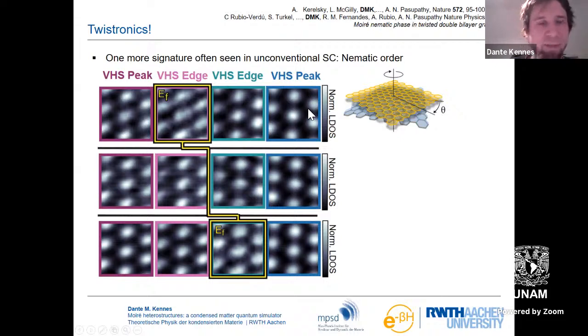So these are STM measurements. You can think of this as probing the local density of states. And let's first look at this far right panel here. This is at a filling where you are far away from this insulating state. And what you see is a nice C3 symmetric pattern. That means you rotate by 120 degrees and it's symmetric. Now let's tune into the insulating state. What you see, shown for example in this panel highlighted in yellow in the upper row here, is that you find these stripes emerging. These stripes pick one of the three directions that you have available and obviously break the rotation symmetry that you had in the previous system.